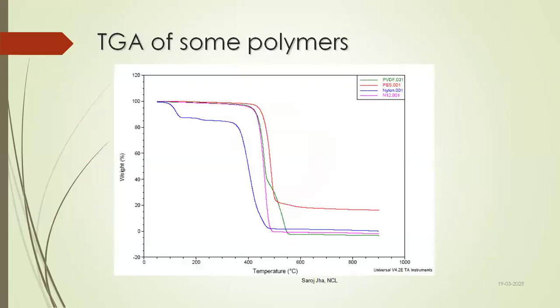Suppose in the polymer industry, you get a sample which looks similar. All polymers look similar. By looking at the polymer, you cannot identify which polymer is what. So what do you do? You first do a TGA on that using the experimental conditions which I showed you just now, and find out the degradation temperature of that material.